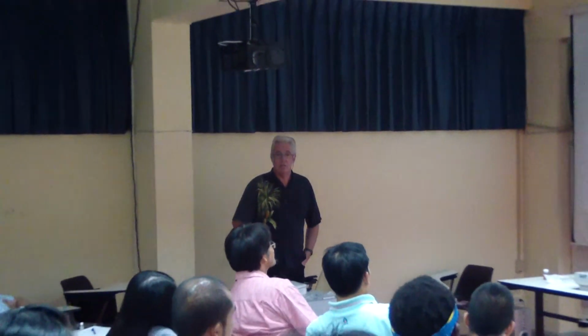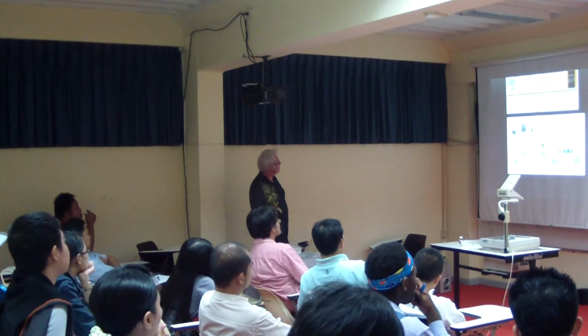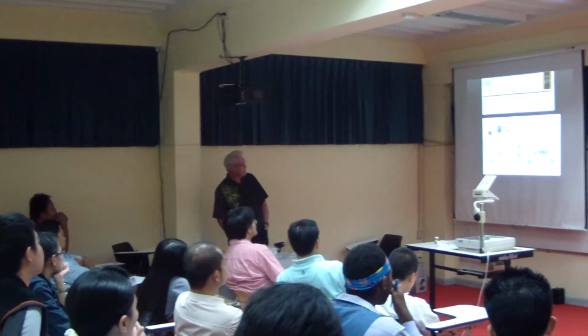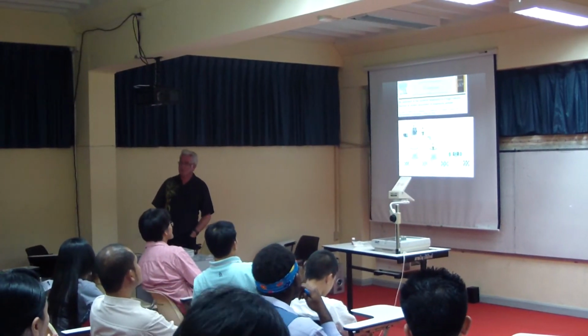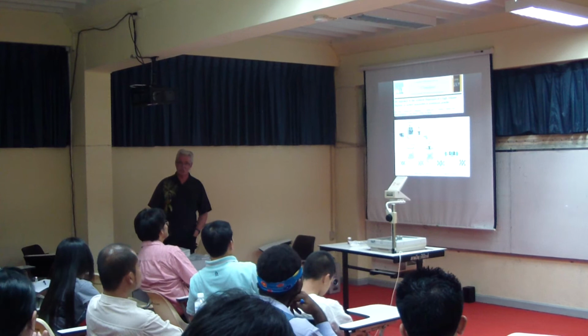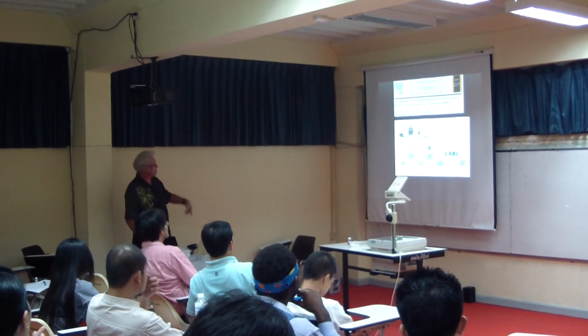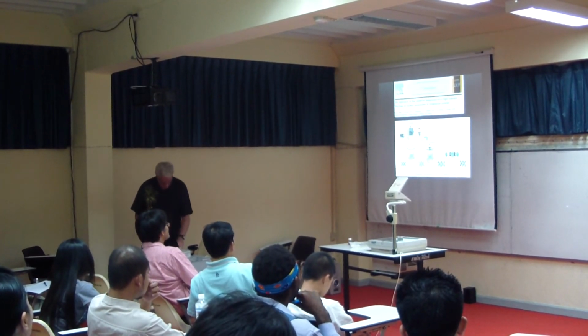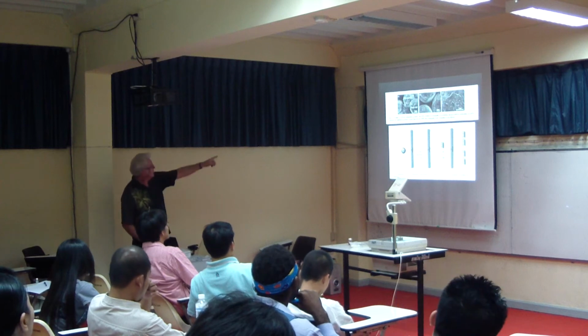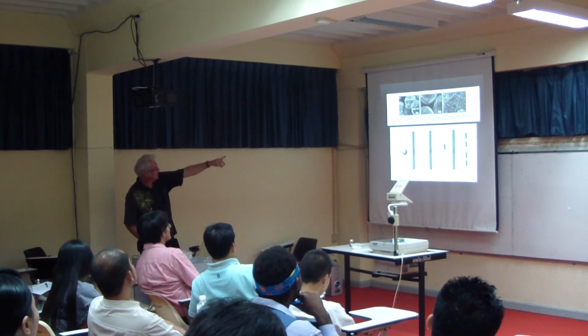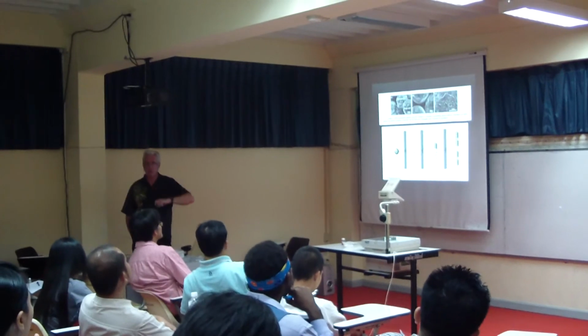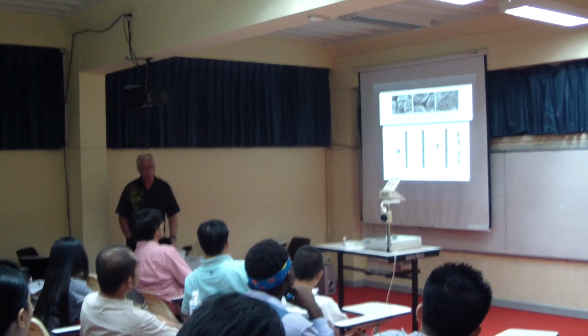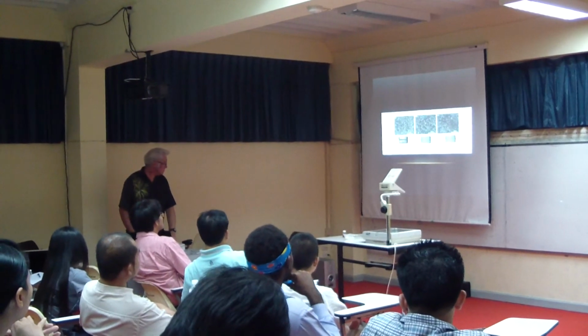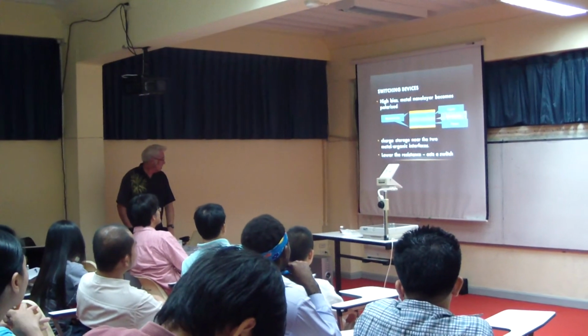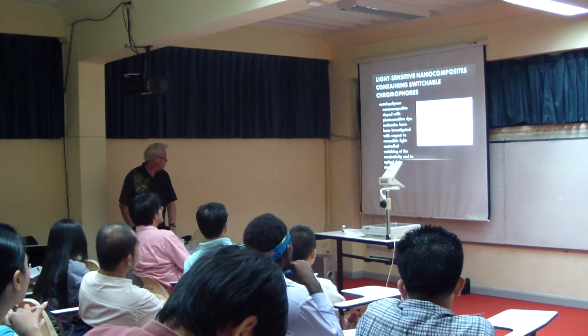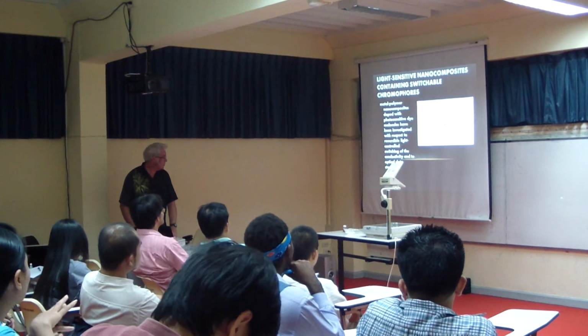As I said, with this one we did some work with some Chinese colleagues putting carbon nanotubes into aluminium, which is a difficult task as well. We're interested in getting uniform distribution, and we managed to do that. You can see there in the top right-hand corner, those are the carbon nanotubes coating the aluminium powder before we hot press. And you can get all these different sorts of nanocomposites.